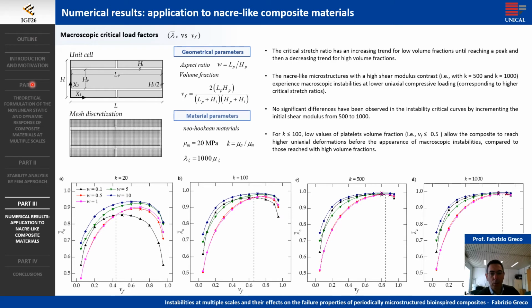We start now with the numerical results by determining the critical stretch ratio corresponding to the onset of elastic instability with long wavelength, by analyzing the macroscopic instabilities in uniaxially compressed nacre-like composite materials. A parametric analysis with respect to the main material and microstructural parameters, including shear modulus contrast, platelets volume fraction, and platelets aspect ratio, has been carried out.